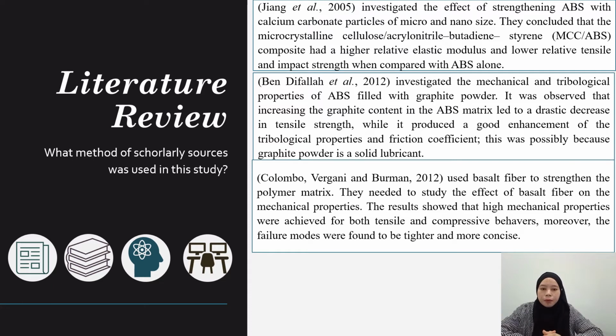Next, we move to the literature review that I used in this study. First, Jiang 2005 investigated the effect of strengthening ABS with calcium carbonate particles with micro and nano size. They concluded that the composite had a higher relative elastic modulus and lower relative tensile and impact strength when compared with ABS alone.